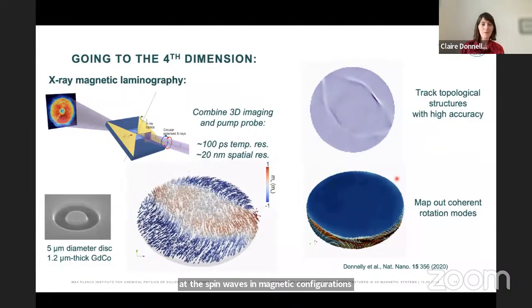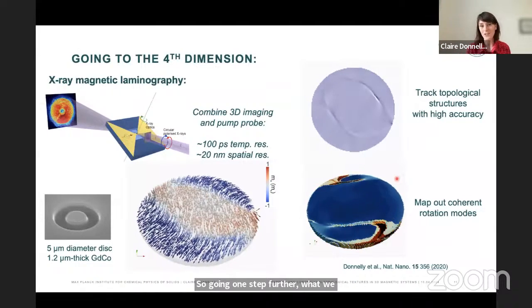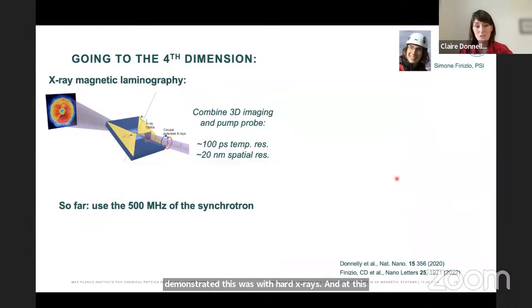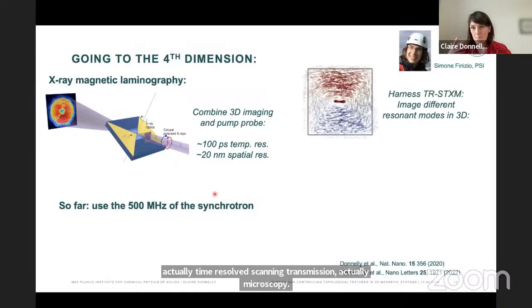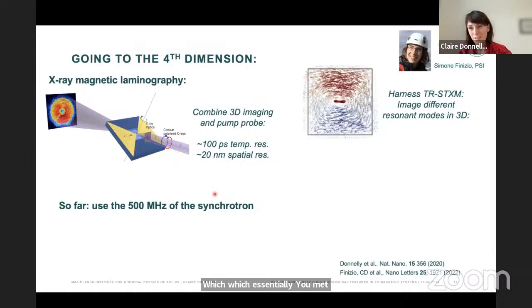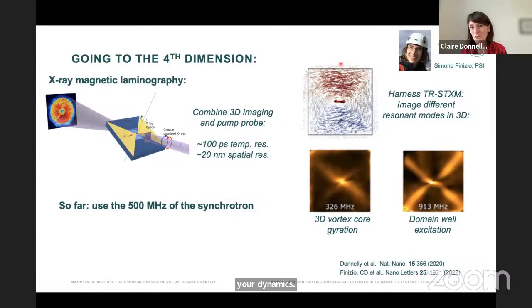So going one step further, what we had first demonstrated this was with hard X-rays. And at this first point in time, we were actually limited to about 500 megahertz, so to the 500 megahertz rate of the synchrotron. But by combining it with a different technique, which is soft X-ray time-resolved scanning transmission X-ray microscopy, which essentially uses a point diode, so a much faster detector, you can actually then start to look at resonant dynamics in 3D. So by tuning the excitation frequency of your system and also the frequency at which you can record your dynamics.